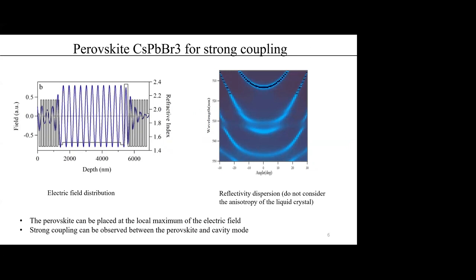We designed the liquid crystal microcavity by using the transfer matrix method. Firstly, we do not consider the anisotropic refractive index of the liquid crystal layer, and just assume that the refractive index of the cavity layer is around 1.5. In this microcavity, we put the perovskite material onto the surface of the bottom DBR with the center wavelength of the stop band at around 530 nanometers. From the calculation, we can see that the electric field here can reach a local maximum at the position where the perovskite microplate is inserted. In addition, our calculation shows that strong coupling can be realized due to the large exciton binding energy and oscillator strength of the perovskite microplates.